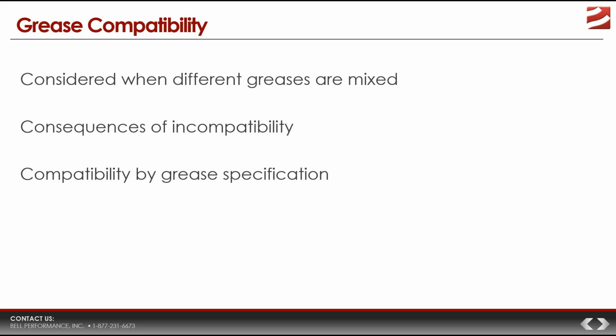But there are three other specifications you'd want to examine because they give important indications of whether two greases are compatible. First is dropping point. If the dropping point of the two greases is similar enough, then when you mix them together, the overall dropping point of the mixture doesn't change all that much, and that's good. You want the overall dropping point of the old grease and new grease mixed together to stay close to what it was before, so you want dropping points to be similar.